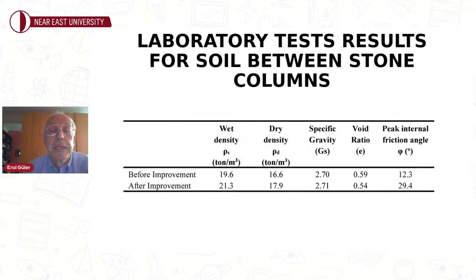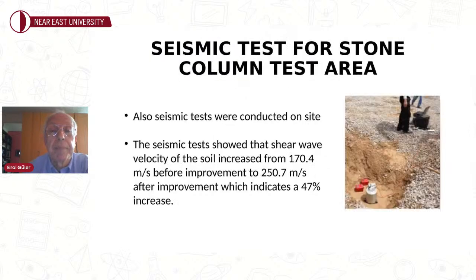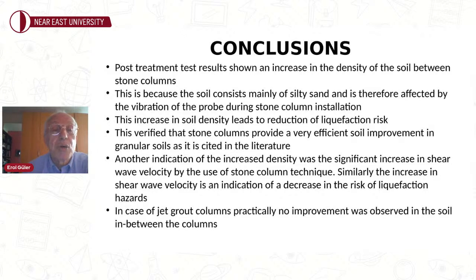When we look at the laboratory tests, there was a significant decrease in the void ratio for the stone column. Before the improvement, the void ratio of the soil in between the columns was 0.59. It reduced to 0.54, and the friction angle significantly increased. As I mentioned, we also conducted shear wave velocity measurements, and it was determined that after applying stone columns, the shear wave velocity of the soil increased from 170.4 meters per second before improvement to 250.7 meters per second after improvement, which indicates a 47% increase.